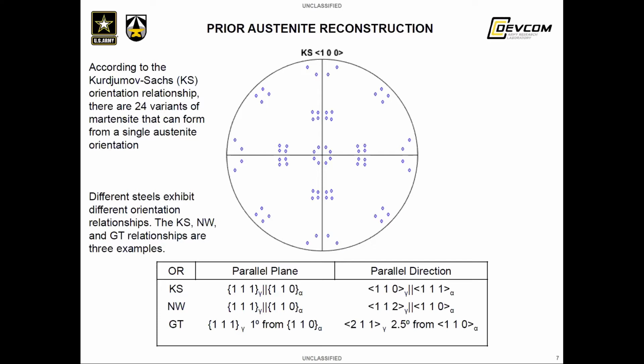This set of orientations, being the set of martensite crystal orientations that can form from a single austenite crystal, are the circles of the circles and bars, centered around the 100 poles of the parent austenite orientation. So in this pole figure, the austenite grain that formed these theoretical 24 variants is unrotated from the frame of the pole figure. Beneath the pole figure, there's a table that defines a few other orientation relationships, which again depend on the type of steel being studied.